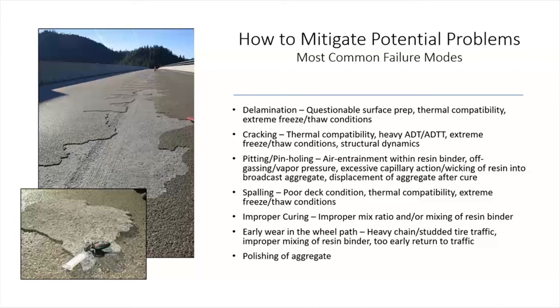This is an interesting photo. Like I said, many of these photos I took over the years. This particular photo was at a high elevation in the mountains. In this particular state, when they first started using thin overlays, they thought that three layers would be better than two. It's like a rubber band. A thicker rubber band is not as flexible as a thin rubber band. And when you talk about expanding and contracting, the coefficient of thermal expansion of the overlay being higher than the bridge deck, it's usually not too much of a problem if the deck is sound and solid. But if you put three layers and it's not as flexible and you've got a lot of thermal cycling and you're at high elevation with a lot of freeze-thaw and thermal cycling, this is what happened.